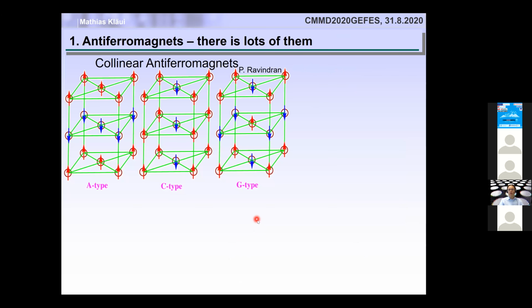And why is it that we have so many more antiferromagnets? Well, that's because there are many, many options on how to generate an antiferromagnet. So you can see here that if you have an antiferromagnet, you just need a zero net magnetization. And that means, for instance, you can have a layered antiferromagnet, whereas in one layer, all the spins point up, and in one layer, all the spins point down. And then you can have a different version where you have within a layer up and down spins. However, in all the layers they're the same, or you can combine both, where you have within a layer different orientations of the sublattices, and then also in different layers these switch as well. So these are very different orientations, and these are actually realized in reality.